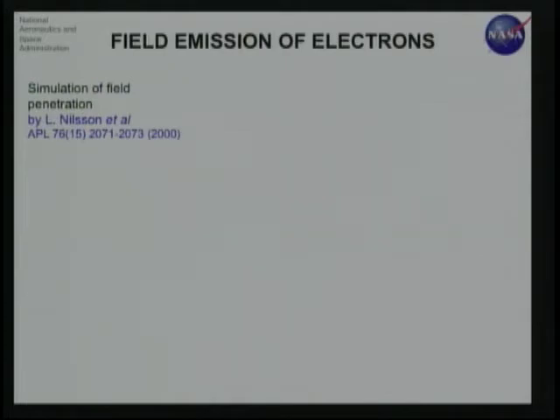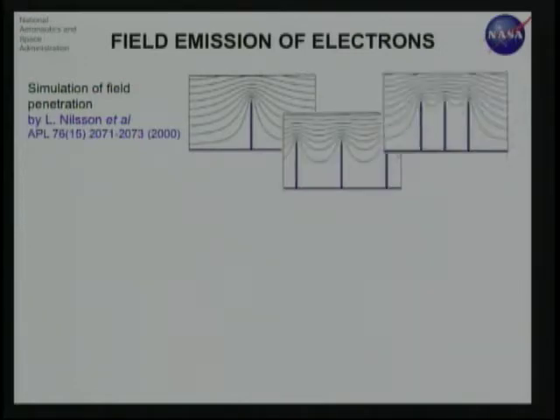There are many techniques that have been done in the past, and through simulation, when you have a single field emitter, you need a very good field penetration to make sure that it is emitting efficiently. And when you put multiple emitters together, this is a well-known problem that people use all the time in RF shielding: electrostatic screening among the conductors. So your field penetration is not great, which means not all emitters will be emitting at the same time or at the same efficiency that you want them to.